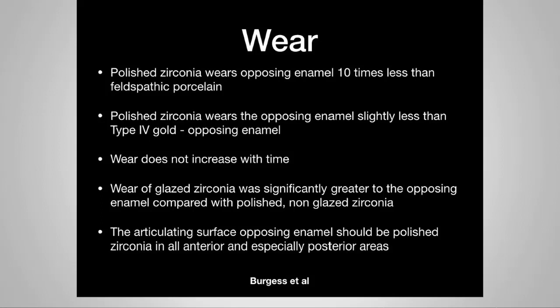So I think the take-home point from the wear side of it is all surfaces should be polished, anything that's going to touch an opposing restoration or tooth or crown or whatever else. You can talk to your lab about polishing the surface, or you can certainly take a polisher. If there's a glazed surface, you really should go ahead and take a polisher over that glazed surface. If you adjust it and form a rough surface, you must go back with the proper polishers and polish that. If you do that, then wear becomes a non-issue. You can see that even compared to gold, it's going to be quite kind to the opposing dentition.